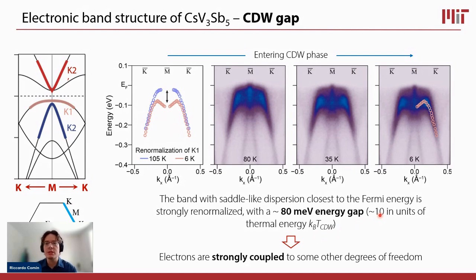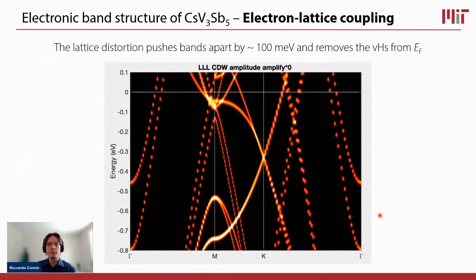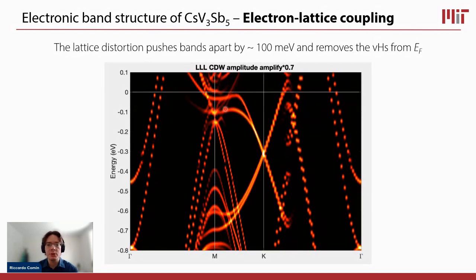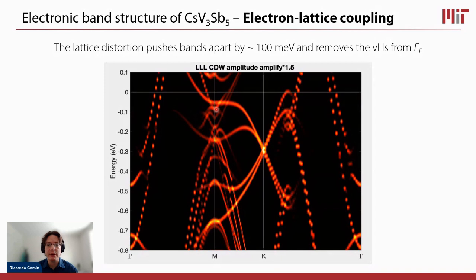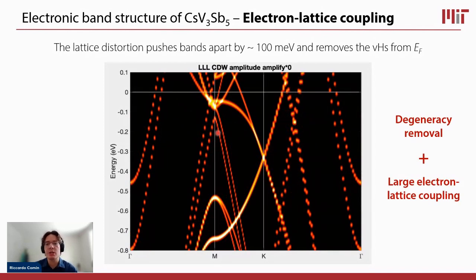I'm almost done. I'm going to wrap up now just to show one last thing, which is what happens if we take the density functional theory electronic bands that we calculated and artificially distort the unit cell in the way that we expect to happen at the charge density wave transition. If you progressively distort the unit cell, you see that these bands, at the M point, at the Van Hove singularity, get pushed down by a very large amount, of order hundreds of milli-electron volts. So what we're witnessing is that these degeneracies at the M point, at the Van Hove singularity, are being removed by the lattice distortion. And this happens because there's very large electron lattice coupling at play in this system.